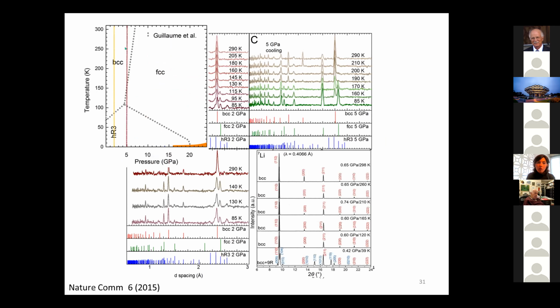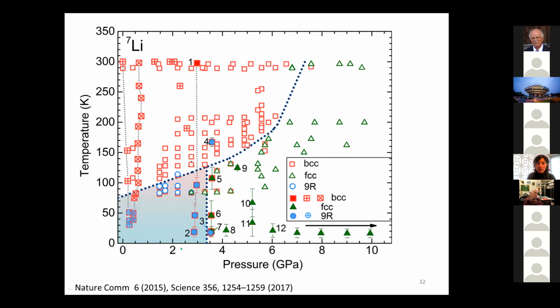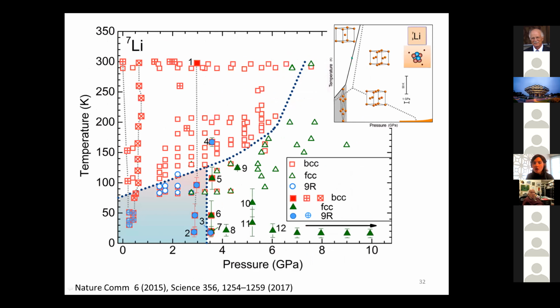that when we are cooling down from FCC, if we enter FCC, we stay in FCC. And we basically completed this work by doing these measurements on lithium 6 and lithium 7. The red squares are showing BCC, green are showing FCC, and blue is showing mixed phase, this Martensite. And we saw that these hypothetical boundaries actually are not valid. And this is where we're going to end up. We cool down from BCC, we end up in this 9R structure.